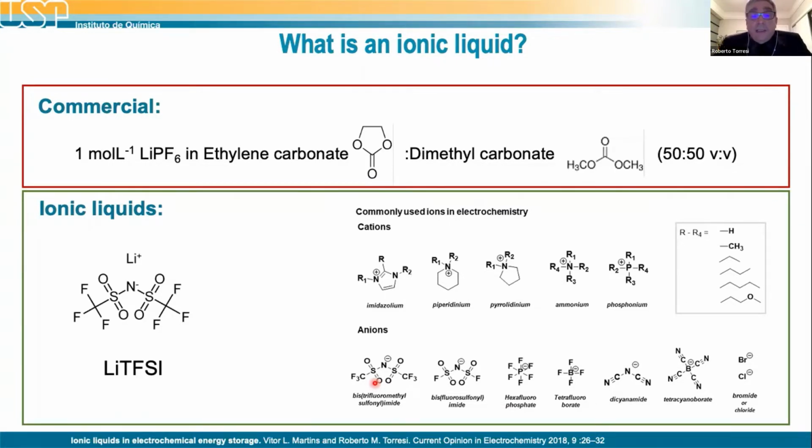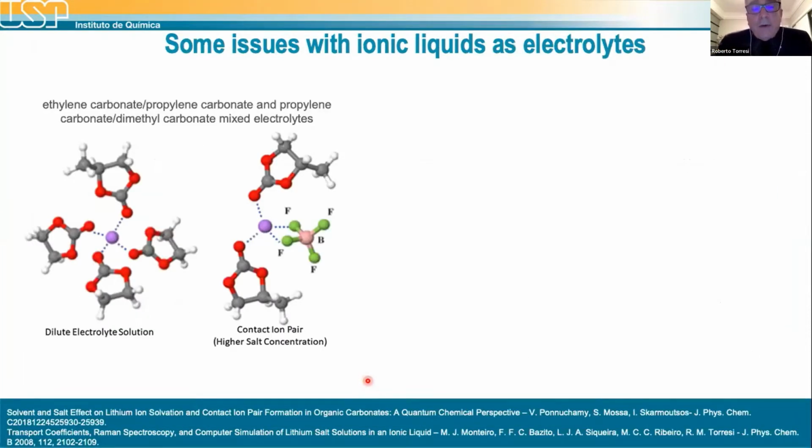conductivity. So in this liquid, you have only cation and anion. There is no neutral molecule of solvent, and of course that gives you a liquid with a high viscosity. This is not good for us for electrolyte. However, we can work on it, trying to decrease viscosity and to have other important properties. So, how these properties are fixed in the case of ionic liquid.